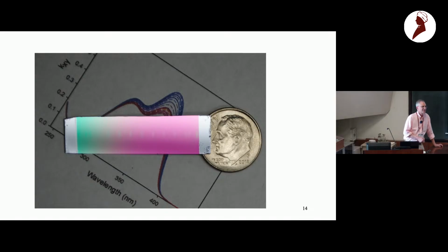Did you analyze the surface roughness while depositing? We analyze the surface roughness after deposition. We don't do it during deposition. I'll tell you, if you stop at various points, what you find is if you deposit just a little bit, it's super rough because it hasn't yet formed a continuous layer. By the time you're at 100 nanometers, most of these films are 100 to 500 nanometers, they're incredibly smooth, less than a molecular thickness in terms of smoothness, which is, again, part of why they're good for OLEDs. Yeah. Okay, so that was orientational order.